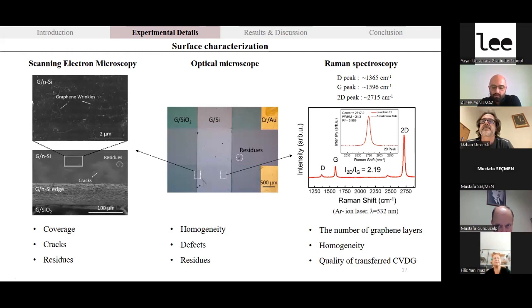One of the fingerprint characterization methods for the number of layers and the quality of graphene is Raman spectroscopy, without any damaging of the layer. Here you can see 3 different peaks: the D peak, G peak, and 2D peak. These are related to graphene. The intensity of the 2D peak with respect to the G peak gives the number of layers.